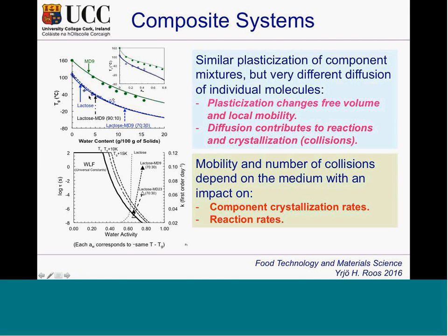The maltodextrin alone is far away, and it tells us that they mixed well together, but their glass transition is not much different. They actually do crystallize very differently because the small maltodextrin molecules, if we have those there, are an extremely good disturbance for the crystallization. What I wanted to emphasize is fractional water absorption.